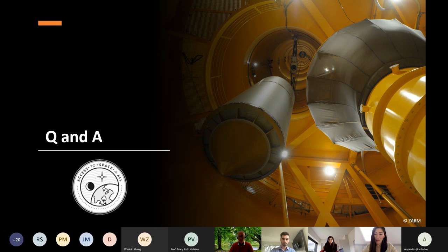Okay, I think they're not affected by microgravity, because generally solid state phenomena are not that much affected by gravity. It's really when you have a liquid or a fluid in which there is a variation in density leading to sedimentation, buoyancy, natural convection, etc. That's really where you see a difference between microgravity and Earth, which is why I mentioned that of the manufacturing processes like metal forming, rolling, etc., in which you have plasticity and dislocation mediated deformation, these are not really subjects for microgravity research.